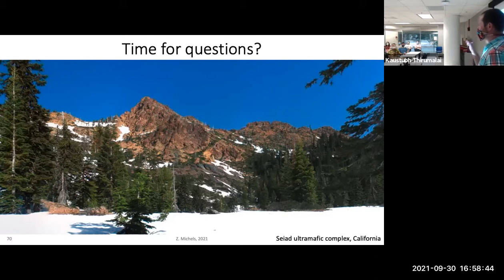The nice thing though about a lot of these techniques like EBSD is that the software controls the step size. And so even though your interaction volume may be bigger than your step size, there's enough difference in what's being analyzed at each of these steps that you can actually resolve data sets that are better than the images you would get from the electron image. So it kind of depends on the analysis you're doing. If you're really interested in nanoscale stuff, what I would say is let's try it, because that's something I'm interested in, pushing the limits of this. But if we can't do it here, the good news is that the Lunar and Planetary Labs has a couple different electron microscopes, one that's just like ours, and 2 that are field emission guns, where you can resolve better scale.